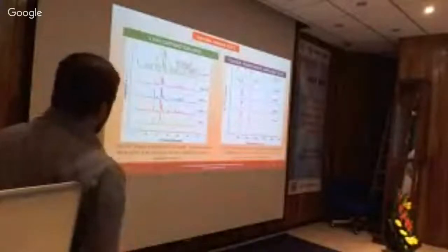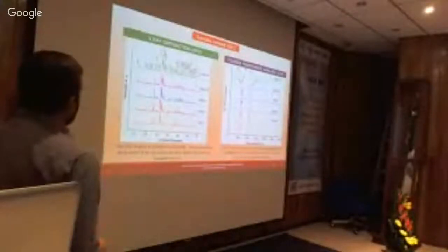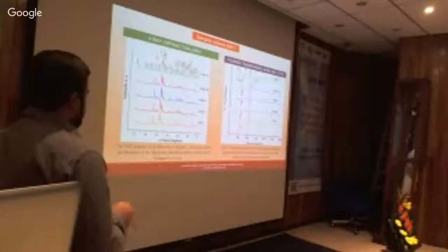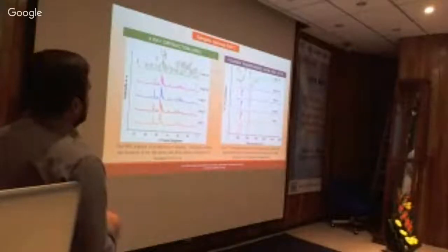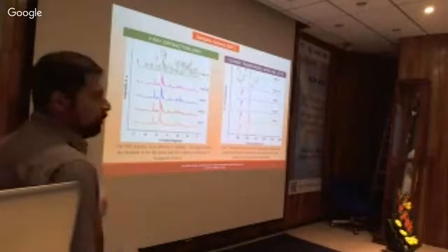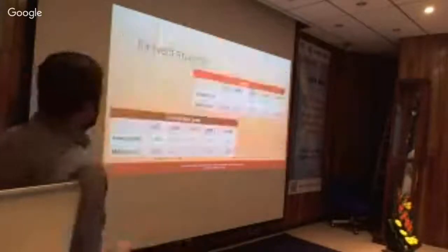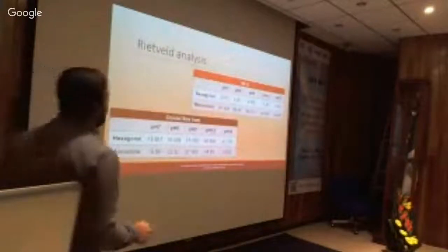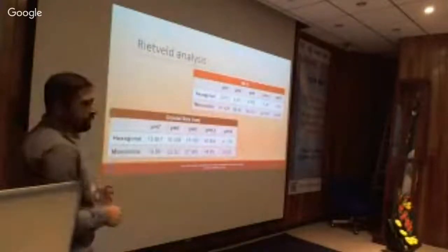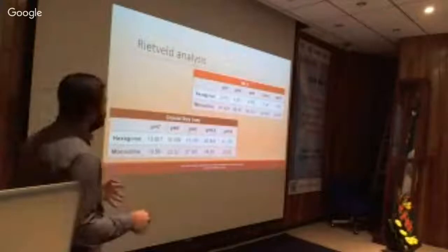And these are the XRD patterns and the FTIR of the different pH values of the hydroxyapatite structures. We can see here it presents all the peaks of hydroxyapatite, and at first glance hexagonal, but we did the XRD two-phase Rietveld analysis, where we can get the weight percent of each phase present at each pH.